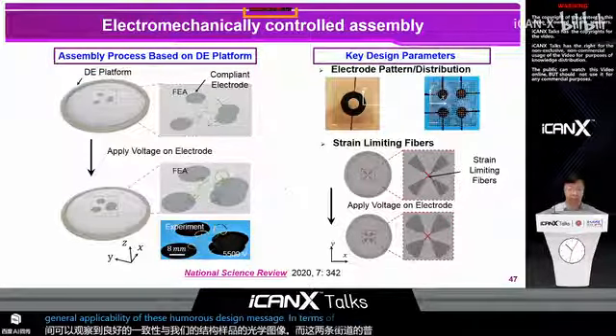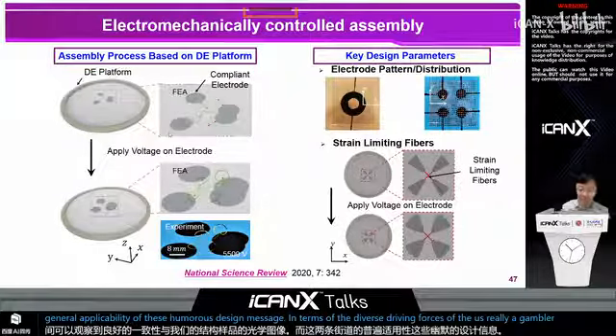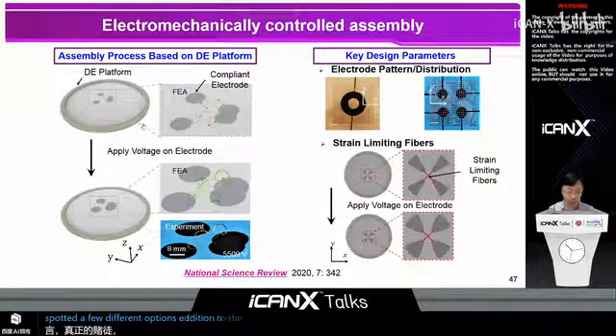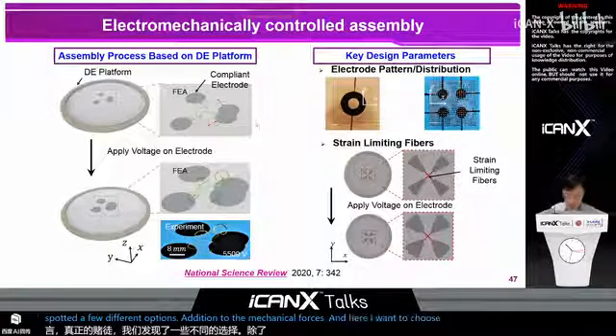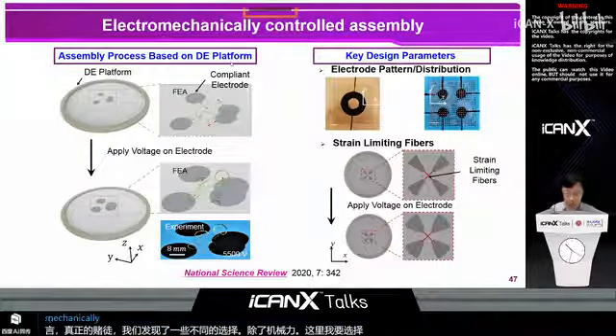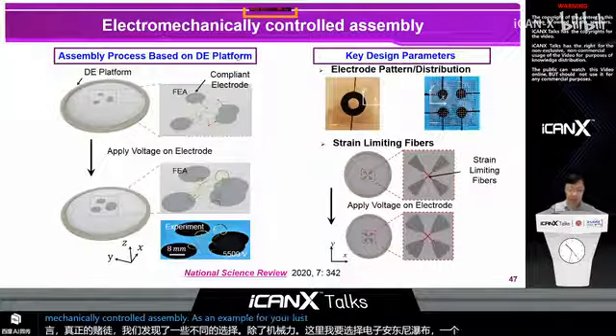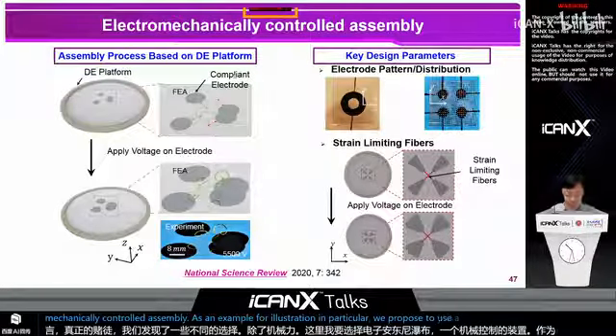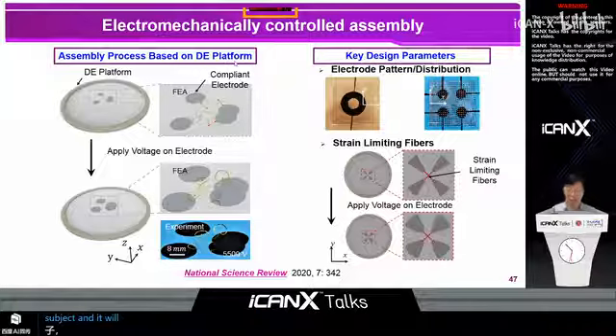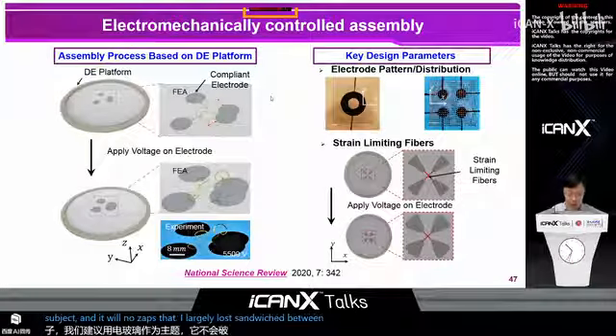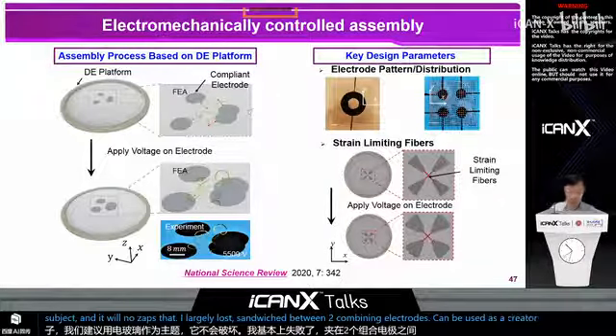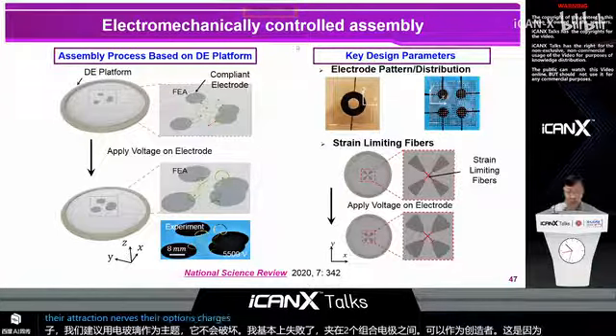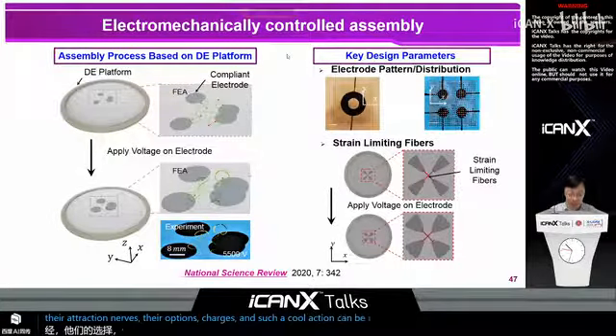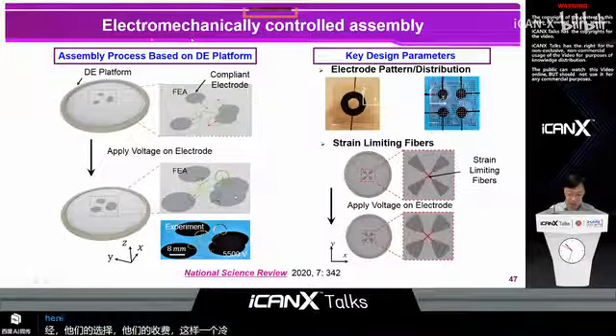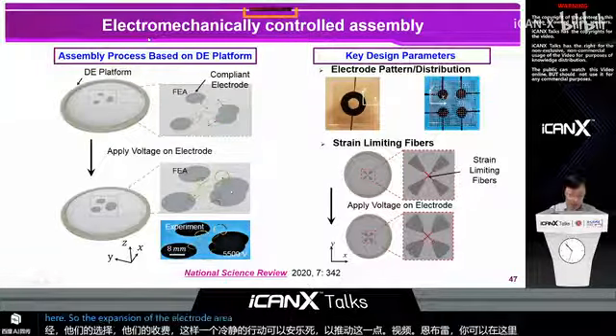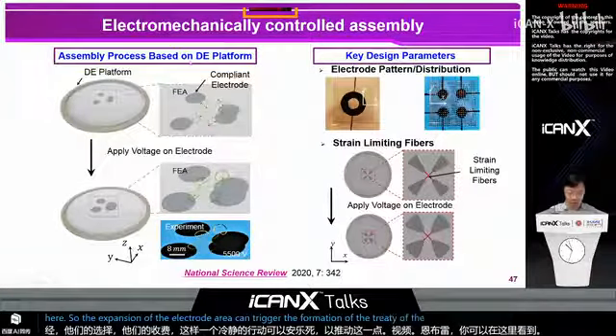Then in terms of the diverse driving forces of the 3D assembly, we have explored a few different options in addition to the pure mechanical forces. And here I want to choose the electromechanically controlled assembly as an example for illustration. In particular, we propose to use dielectric elastomers to serve as a substrate. And we know that the dielectric elastomers sandwiched between two compliant electrodes can be used as an actuator. This is because of the attraction of the opposite charges. And such an electrical actuation can be utilized to drive the 3D assembly, as you can see here. So the expansion of the electrode area can trigger the deformation of the 2D thin film into the desired 3D configuration.